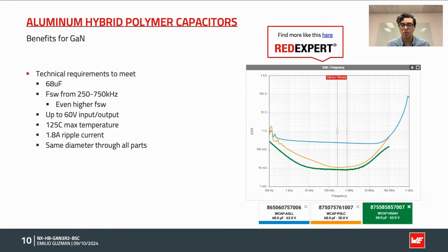The hybrid and the polymer would have been good choices for this design, but the polymer did not meet the minimum voltage. The electrolytic did meet it, but the ESR in that frequency range was too high. And so as Nexperia was looking for the highest efficiency design, it was actually the hybrid capacitor that was the best choice because it met the capacitance requirement, the ESR requirement, the ripple current requirement, and the size.